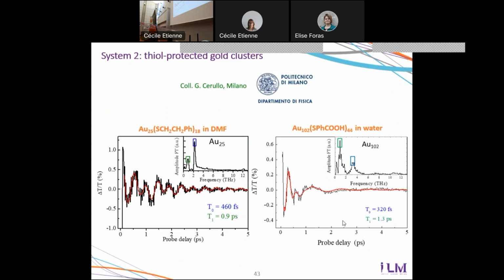So here two time resolved experiments could be done. In this case, it was not one mode that was detected, but two ones with very different frequencies and periods. The reason for this is that such small objects cannot be perfectly spherical. They have some deviation from sphericity, which is sufficient to allow the detection of other modes that are not detectable for perfect spheres.